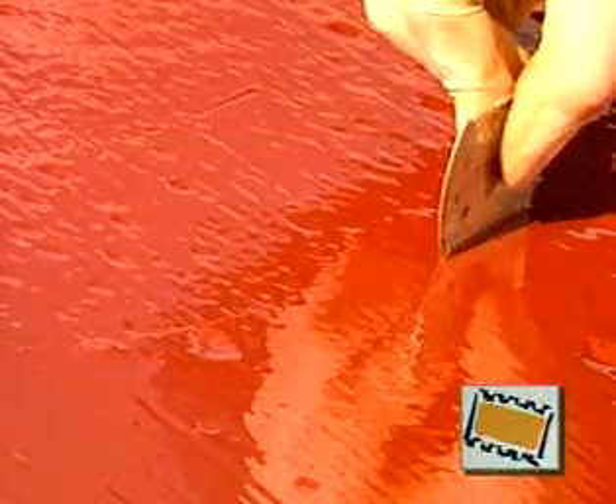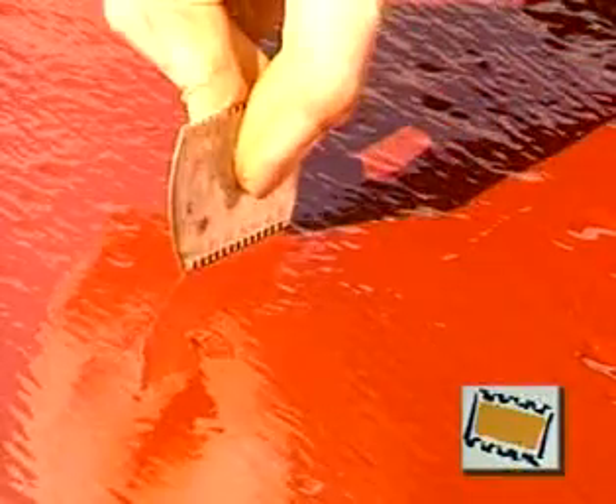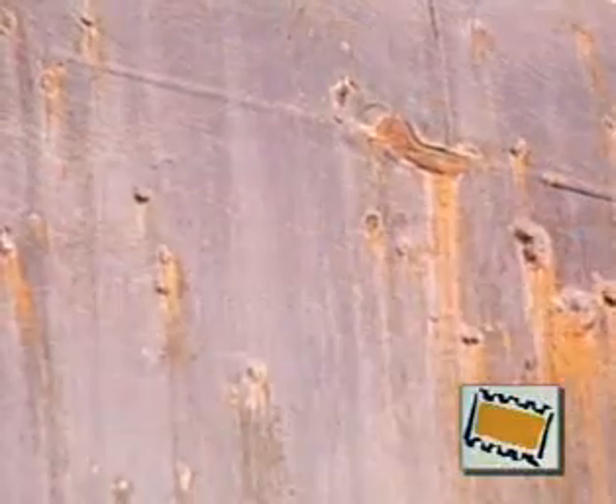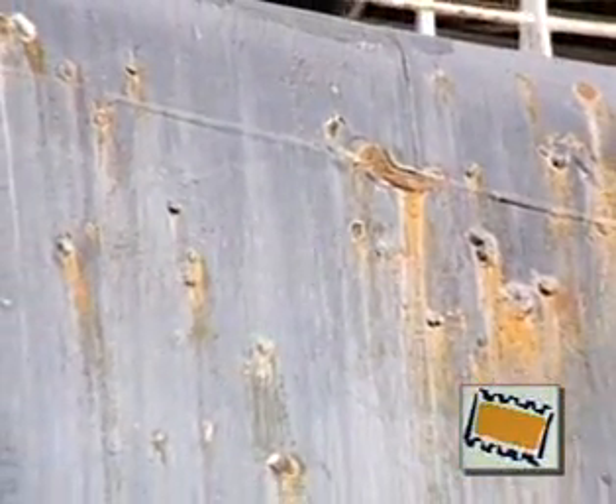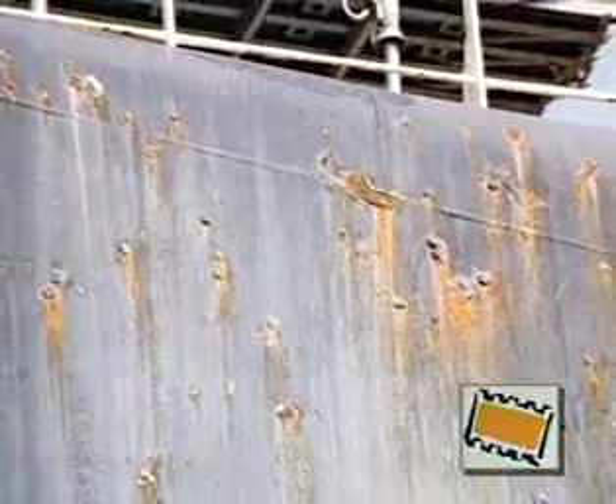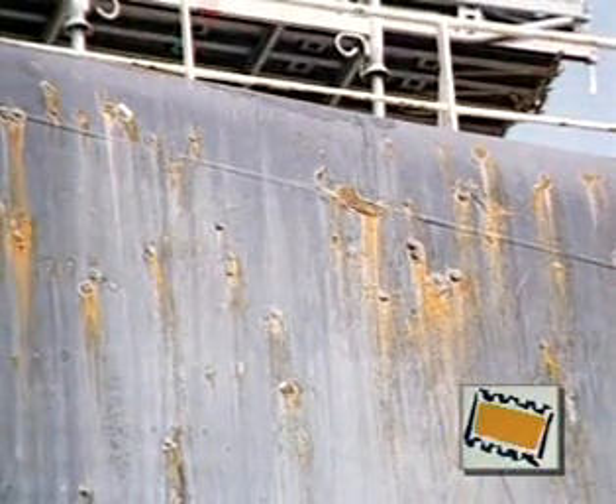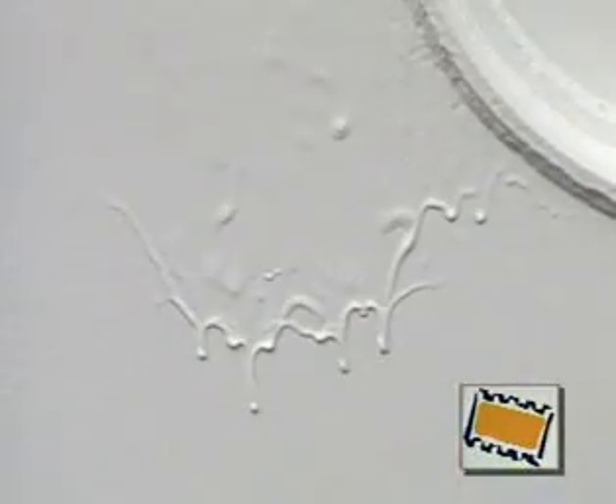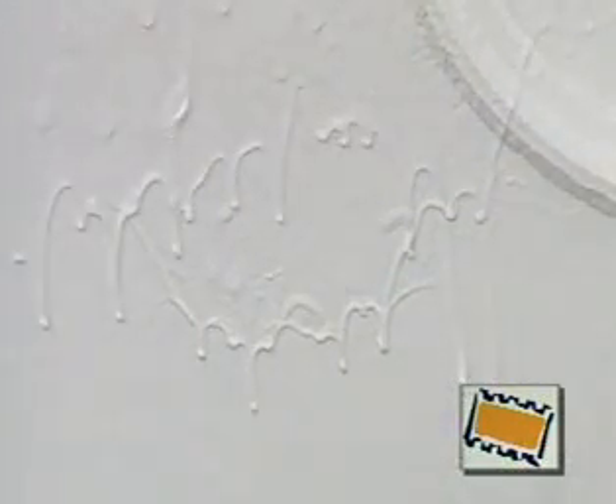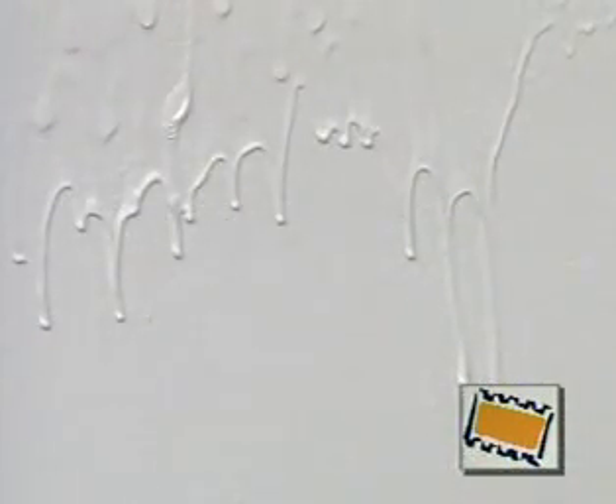Remember, the purpose of the coating is to add a layer of protection over the steel of the ship, both inside and out. If the paint is applied too thinly, corrosion will occur after a short period of time. If the paint is applied too thickly due to over-application, slow drying and film defects such as runs or sags will be the likely result. This will also promote the inefficient use of ship paint stores through overconsumption.